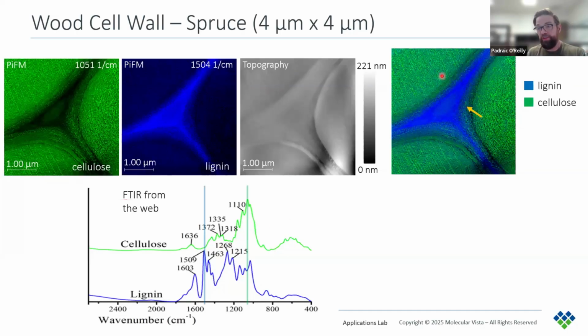Now you can see from these images that the overall composition of this area of the cell wall is these two components. So it's cellulose in green being these sort of outer regions, and the lignin in blue dominating the inside regions. Now they were interested in seeing how this looks more zoomed in, so around where this gold arrow is, because you can see sort of green sprinkled within the blue here.